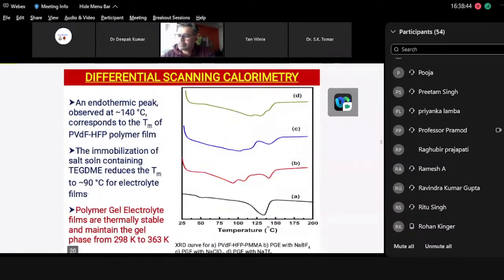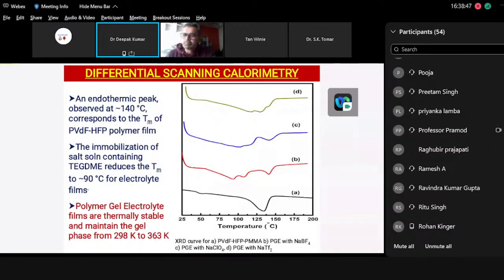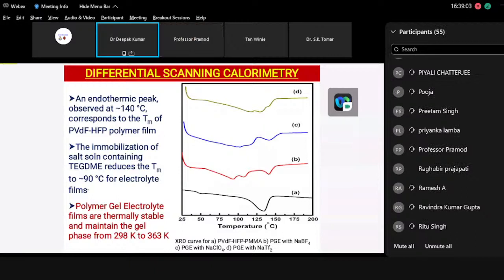For further investigating the thermal behavior of the material, we have also performed differential scanning calorimetry. We observe for the pure PVDF-HFP film an endothermic peak, which is basically a melting peak, observed at 140 degrees Celsius. Once we incorporate the salt solution containing TEGDME and the sodium salts, what we observe is almost all the electrolytes have a melting temperature close to 90 degrees Celsius. So we observe that the electrolyte films are able to maintain the gel phase in a quite satisfactory temperature range of operation.